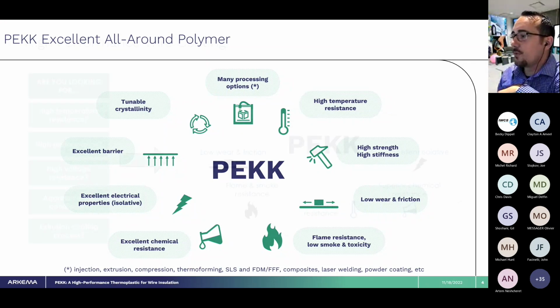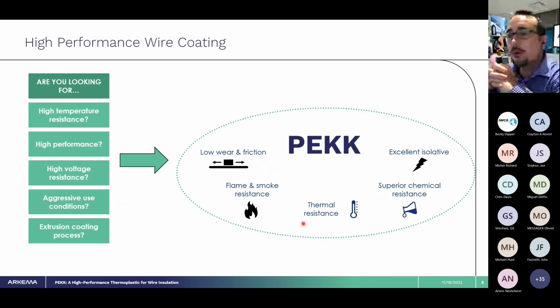Okay, so as far as wire coating, this is going to be a high performance wire coating, if you need all this combination of properties in one jacket for your material, right? So that's high temperature resistance, overall high performance, the high dielectric constant at temperature. You have an aggressive environment, temperature plus wear plus chemicals, and then it's compatible with extruding coating processes, so it's processable on a variety of different existing lines for your application.